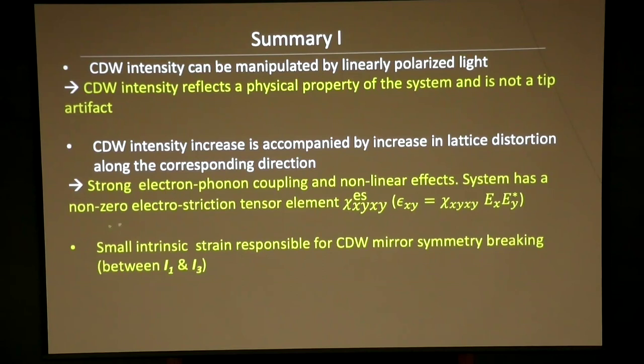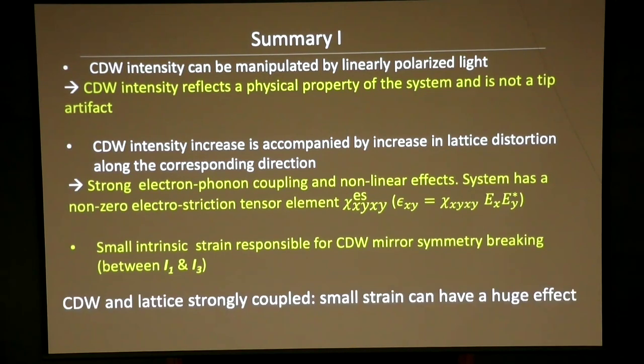It also tells you that the strong charge density wave intensity is associated with a strong lattice distortion in that direction, okay? That means that in this system, the charge density wave is extremely susceptible to strain. Strain is when you change the relative lattice constant in one direction versus the other direction. That's what strain does at the atomic scale. If you did that, then the CDW would respond in this system. Okay? So that's what we've learned from the light.